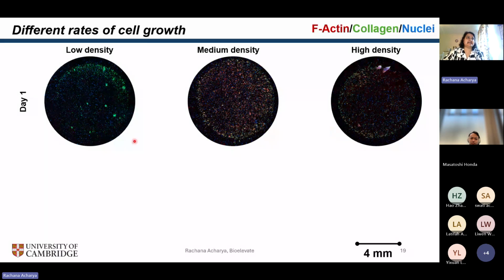This is a confocal microscopy image of the whole scaffold, so that we're not accused of cherry picking and just looking at isolated areas. I put down different densities of my fibroblasts on day one. My low density is 125,000 cells, my medium density is 250,000 cells, and my high density is 500,000 cells. The logic is that as these cells grow, because I have a varying number of cells at the beginning, they are going to grow at different rates, and I might be able to notice that in my electrical devices as well.